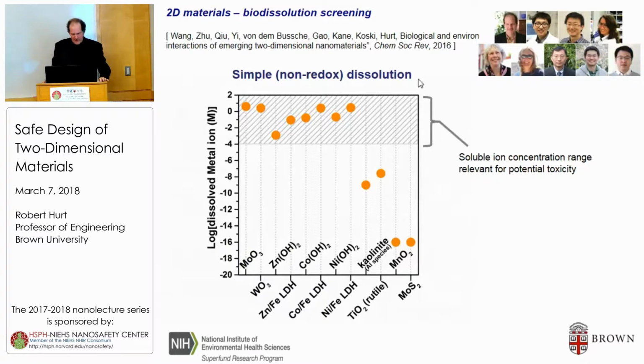And you can start by looking at simple non-redox dissolution processes. And here's a range of 2D materials on the bottom. Here's their published solubilities. And these are for the bulk counterparts where there's data available. And most of them are poorly soluble or insoluble. But you know what people call poorly soluble often are materials that are in equilibrium with a pool of ions whose concentration may be low, but is certainly in the range relevant for potential toxicity in the body or the environment.